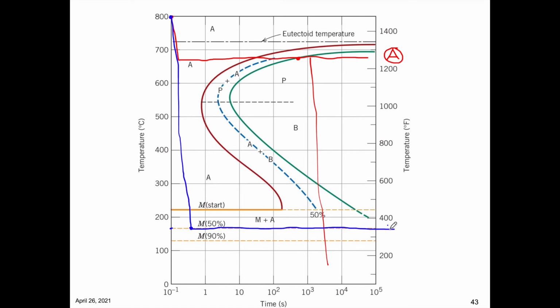And so I'll just kind of put an arrow, right? So that's the only way I'm going to get that. So that's the kind of trick compared to this one, right? If I do any sort of other temperature decreases, that will give me more martensite. So the only way I can maintain that austenite is if I hold indefinitely at this temperature of approximately 175. All right, so that's the trick to that one.